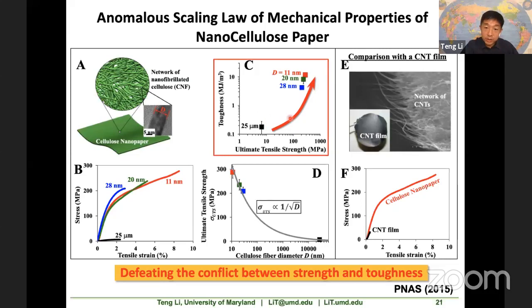To understand the increase of strength as a function of decreasing fiber diameter, we built a fracture mechanics model. And surprisingly, this fracture mechanics model fits very well over the three orders of magnitude of the diameter here, as you can see in the gray line. And it shows that the strength is proportional to 1/√ of the diameter. So this can be understood as the following. When you decrease the building block size, the fiber diameter, you naturally decrease the defect size in the paper. By decreasing the defect size, we know that the strength of the material increases, and it falls very well onto this fitting curve. Now, the next question is: because the building block size becomes smaller, does the material become tougher?